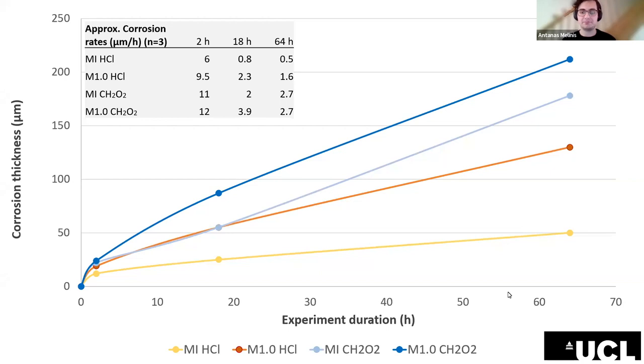Here you can see the results of slightly longer exposure studies: 2, 18, and 64 hours for different conditions in both of these glasses. You can see that on average, the rates are very high during the first few hours, but they taper down as time goes by, likely slowed down by the decreasing proportion of alkali that can still be extracted from the glass surface. And here the M1.0 glasses probably suffered the most damage because they're less protected by their various admixtures, such as iron, alumina, phosphorus, and so on, that feature in the MI glass and increase the chemical durability of these models.